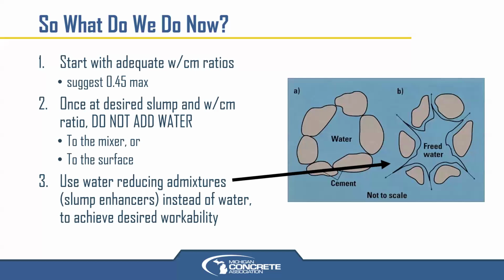So I suggest typically a 0.45 max, but if you're at a 0.45 max, you don't want to hold back a lot of water and batch it at a 0.40 and then have them mix in water at the site or add water on the surface to try to close it up, because then that's not mixed in throughout and it's only on the surface. So stick as close to your mix designs as possible and provide what requires very little adjustment on site.